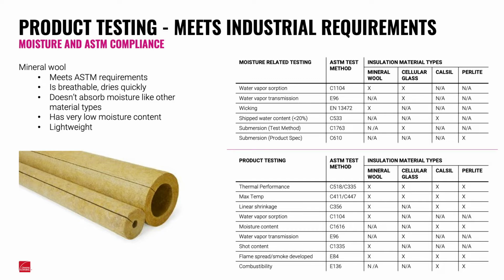Mineral wool has a very low moisture content. So typically it's on the order of around 2%, even though ASTM requirements allow as high as 5% in really high temperature, high humidity conditions. And finally, mineral wool has a very low weight, so it only has about 8 pounds per cubic foot compared with perlite, which is going to have something along the lines of a 15 pound per cubic foot density, so it's almost half the weight.